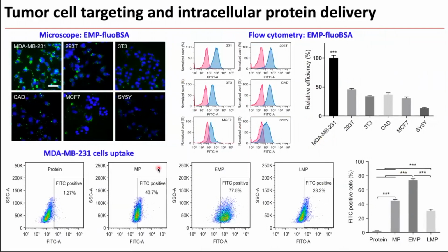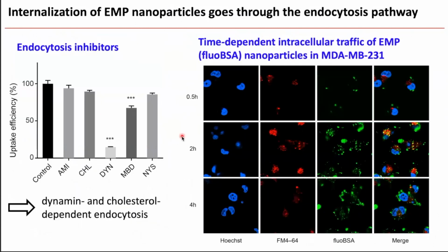cells. And then we also used the same cell line, but with a different protein, the EMP nanoparticles: EMP nanoparticles with the EV membrane, and EMP protein nanoparticles with the liposome membrane, and showed the delivery is more efficient if we envelope the EMP protein nanoparticle with the EV membrane. We further studied the internalization of these particles using different kinds of endocytosis inhibitors, and showed that this is dynamin and cholesterol-dependent endocytosis.